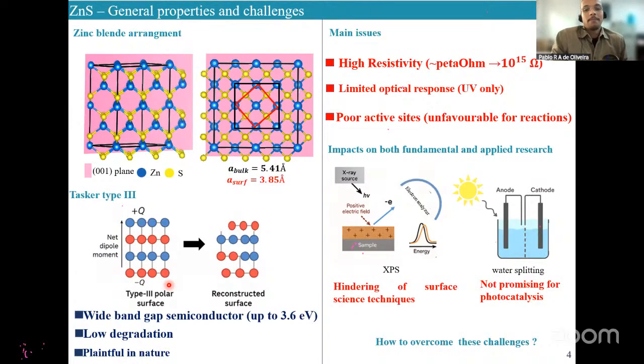However, there are some big issues with ZnS, especially those regarding the high resistivity, on the order of petaohms. This is because ZnS is a huge insulator. I also mentioned the wide band gap, but unfortunately, it is only responsive in the UV range. And if you think about applications in photocatalysis or other kinds of reactivity processes, pristine ZnS does not display active sites, so it is unfavorable for reactions. All these issues together might impact both fundamental and applied research.